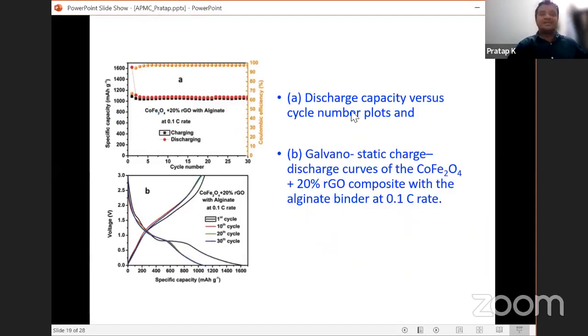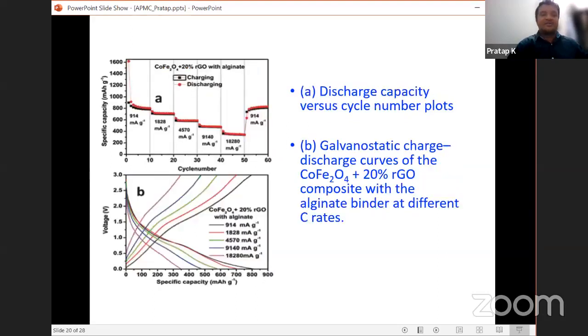So this is the discharge capacity versus number of cycles plot. This is cobalt ferrite with 20% RGO with alginate binder. We are checking with more number of cycles, and initially the capacity is around 1100, and it retained its capacity even after several charge and discharge cycles. So this is called the discharge capacity.